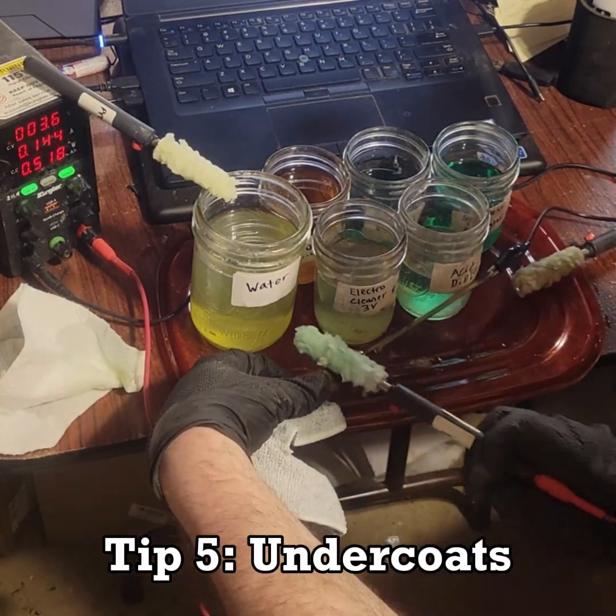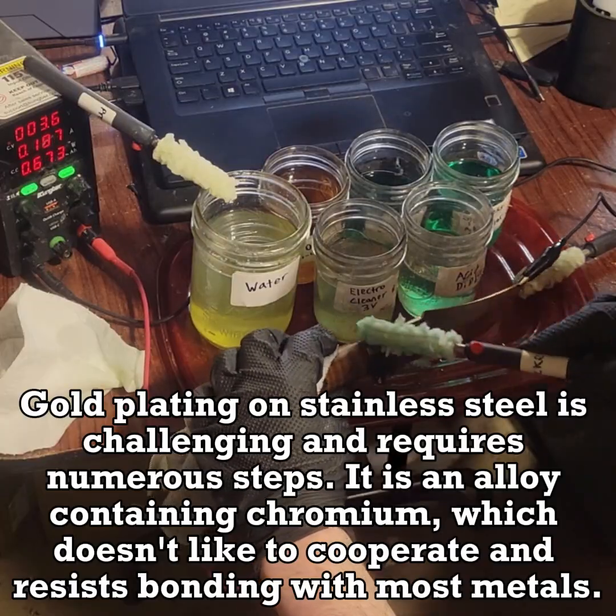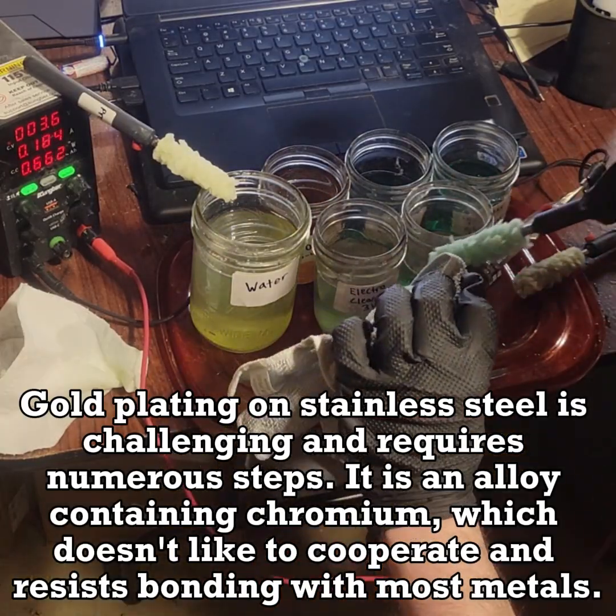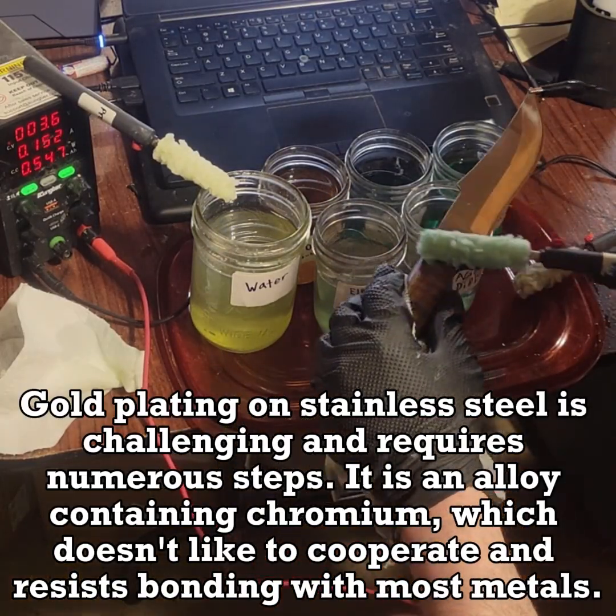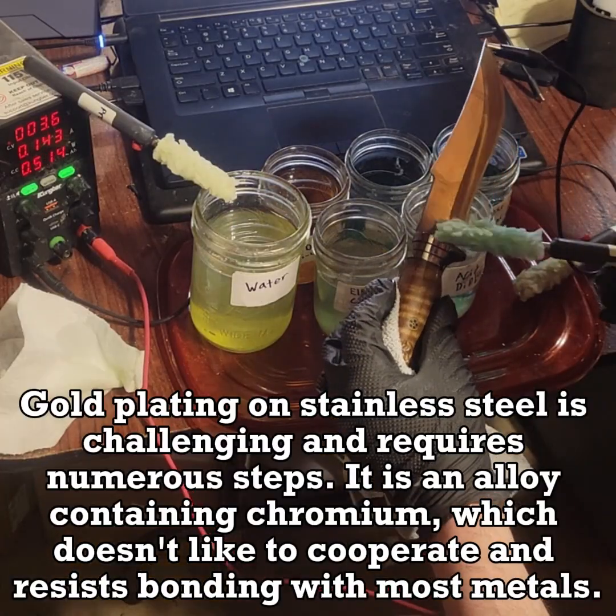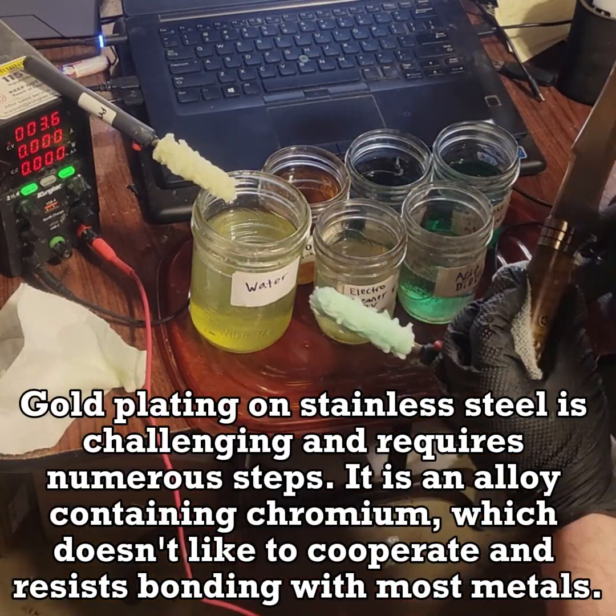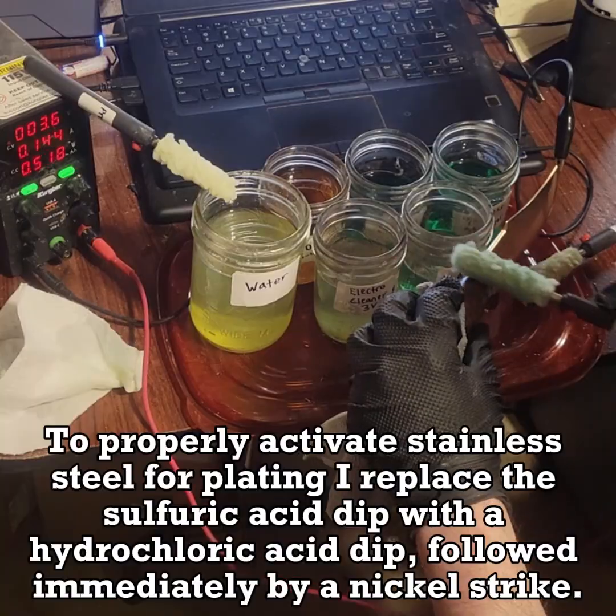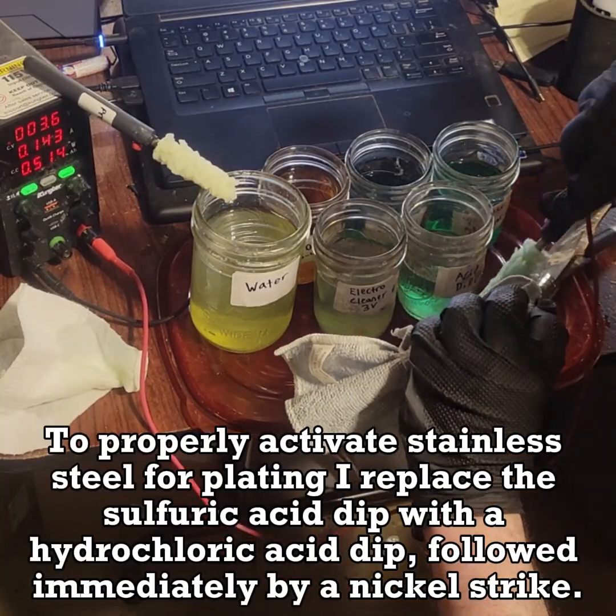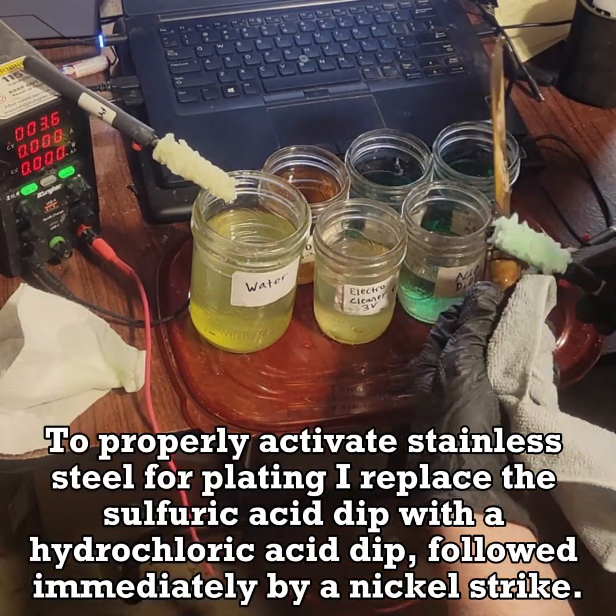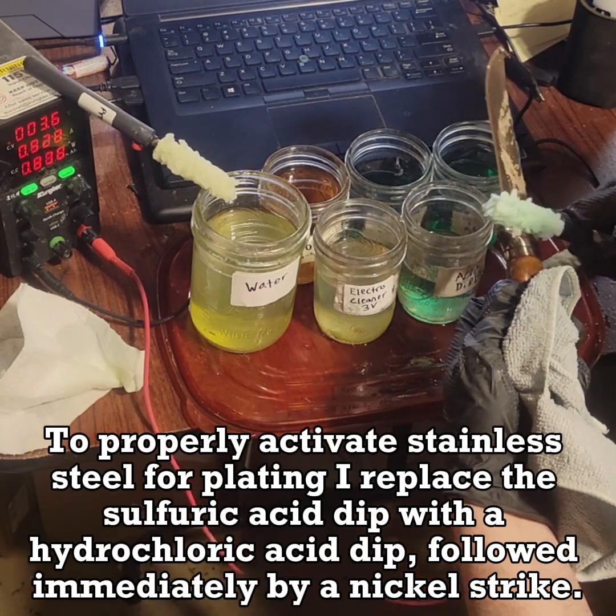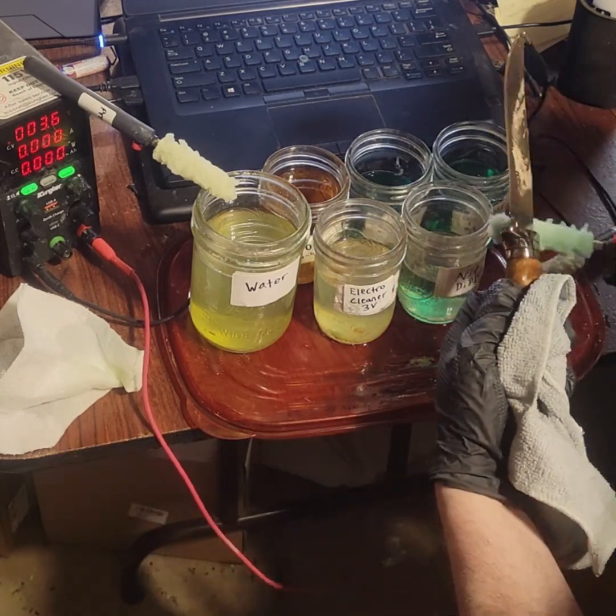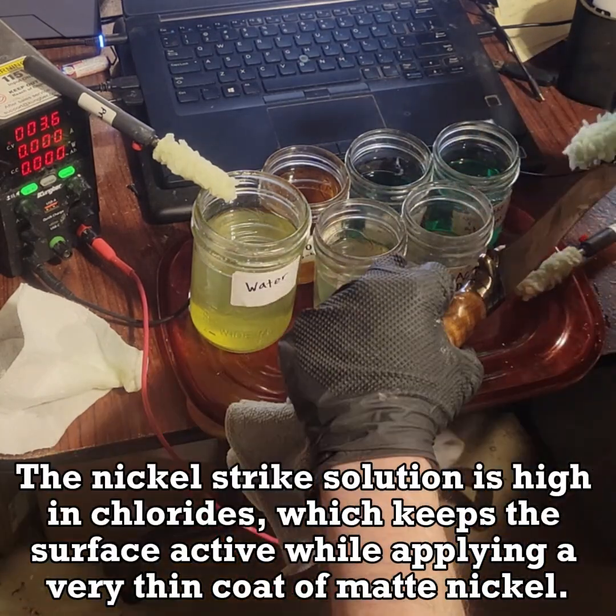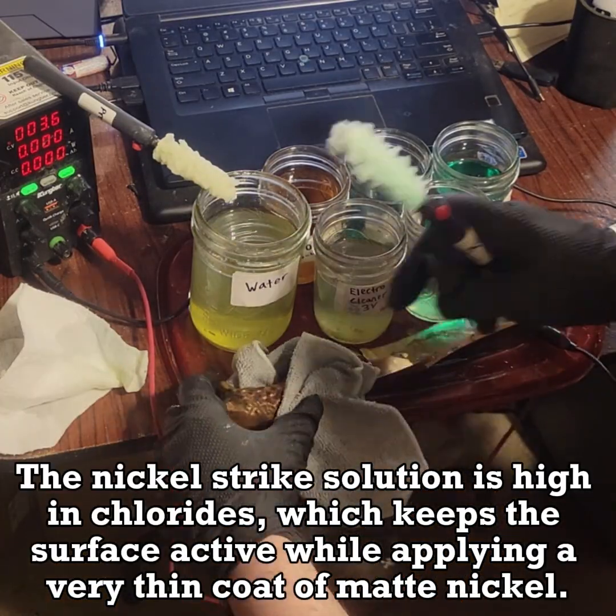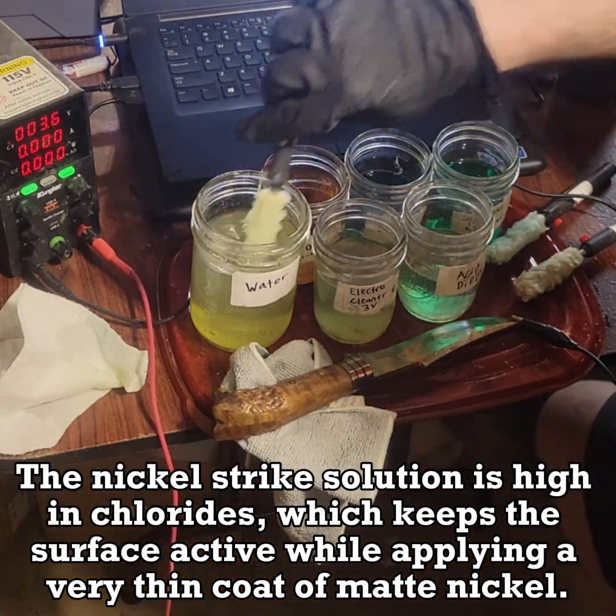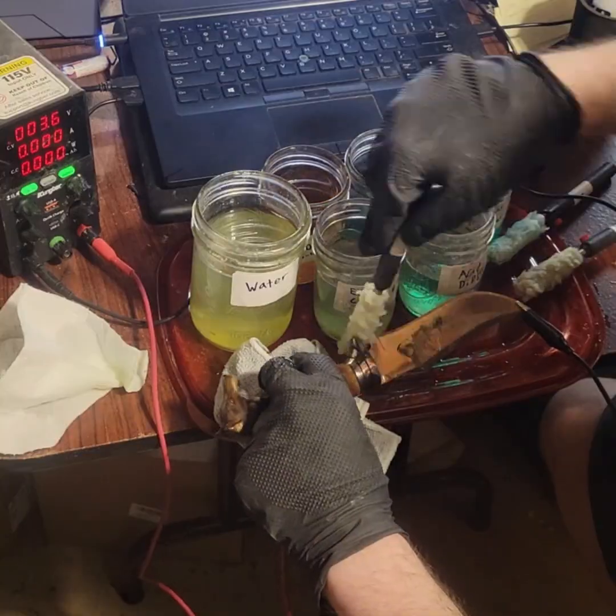Tip 5. Undercoats. Gold plating on stainless steel is challenging and requires numerous steps. It is an alloy containing chromium, which doesn't like to cooperate and resists bonding with most metals. To properly activate stainless steel for plating, I replace the sulfuric acid dip with a hydrochloric acid dip, followed immediately by a nickel strike. The nickel strike solution is high in chlorides, which keeps the surface active while applying a very thin coat of matte nickel.